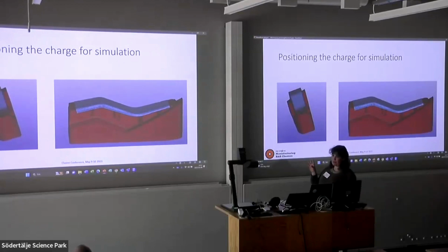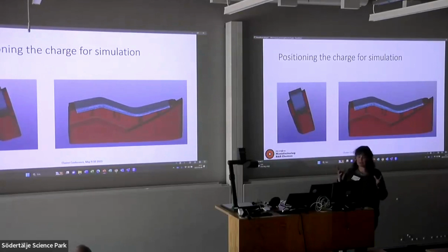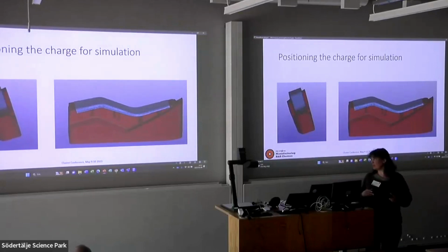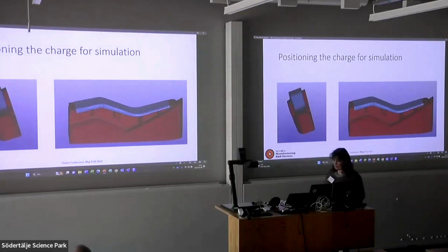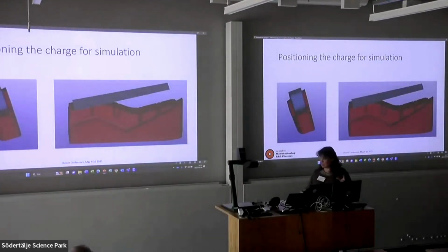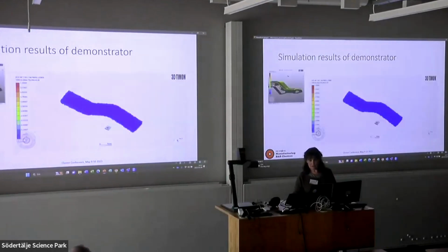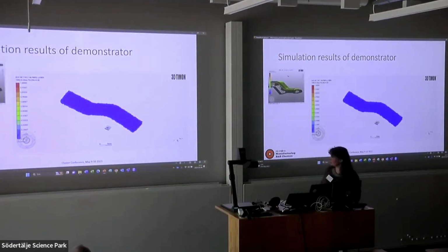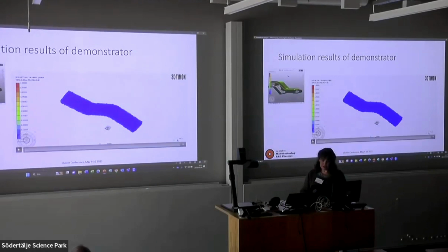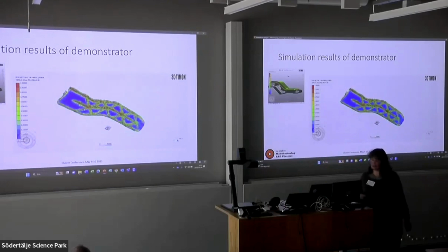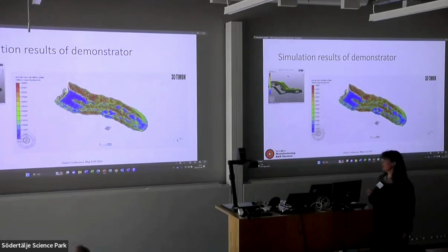It doesn't require much work to be able to put it in place, but by doing this simulation, we get better results. From there, we've just made it into a thicker shell and then imported it into 3D Timon. Then in 3D Timon, you can run the simulation. And here I'm just showing what it looks like when we're looking at the fiber distribution and orientation that you can get from 3D Timon.